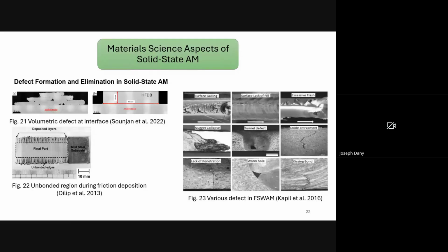There are various surface defects or subsurface defects that occur in friction-based additive manufacturing. The first one is surface galling, which is caused by excessive sticking of material to the tool pin, often due to too high weld pitch or an excessively hot weld, creating protrusions and lumps on the welded surface. The second one is excessive flash, excess material expelled from the joint area caused by excessive heat input or improper tooling force, leading to material overflow beyond the joint line.